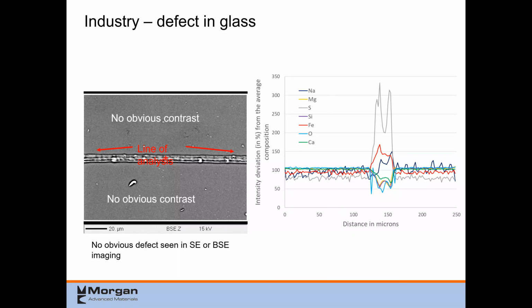So instead I did some line scans in order to figure out what was going on. And it turns out on the right, you can see the line scan that I did. And it turned out that sulfur and iron, so some sort of pyrite, was a large contaminant in the glass. And they were able to find in their process where that was coming in and take care of it.